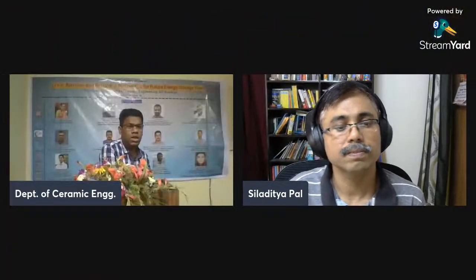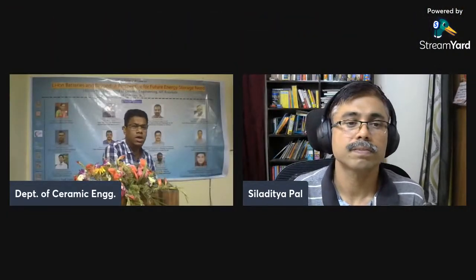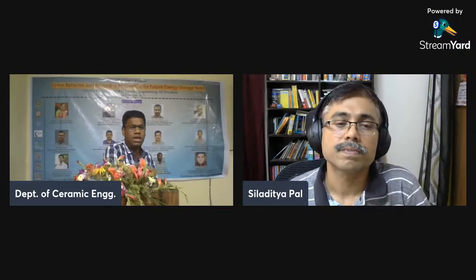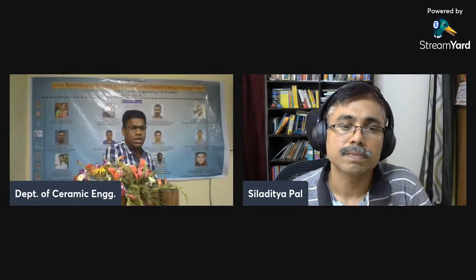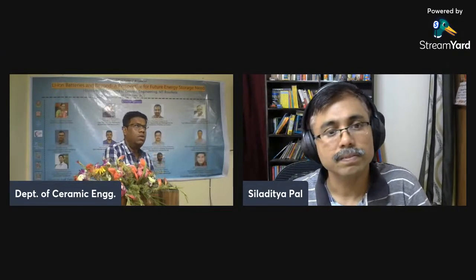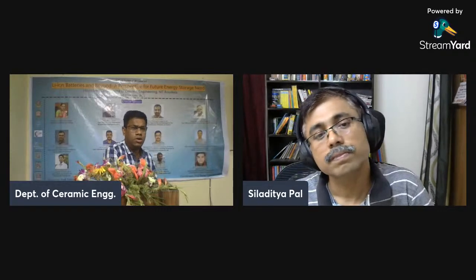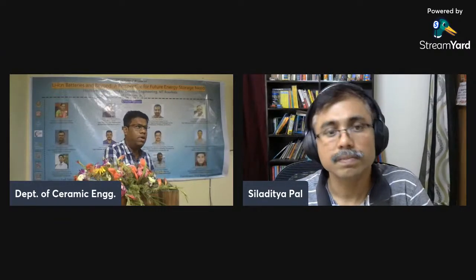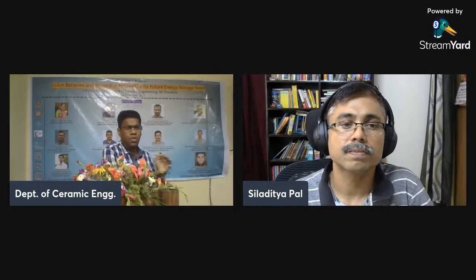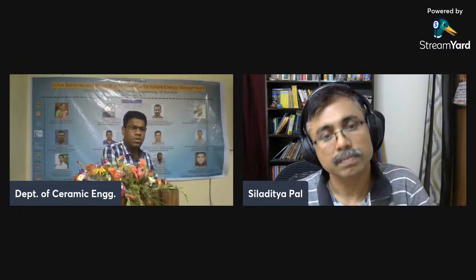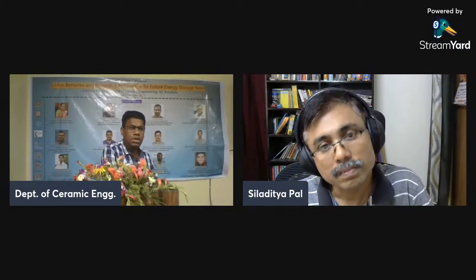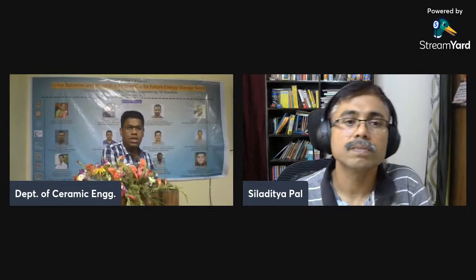Thank you, sir. I have my second question. You mentioned that cracks originate on the particle surface and then move to the interior, right? For lithium manganese oxide, that is spinel LiMn2O4, there is another problem associated with the cathode: Jahn-Teller distortion, if you agree with me. That's why people replace manganese with some other transition metal like nickel.